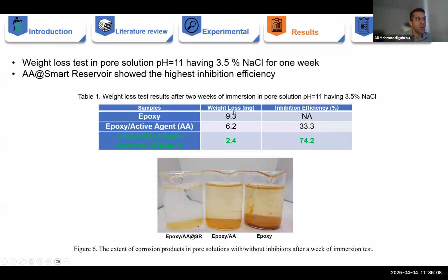And then we observed 9.3 milligram of weight loss for control sample with a lot of rust at the bottom of the beaker, and 6.2 milligram of weight loss for epoxy coating containing active agent, and only 2.4 milligram weight loss for epoxy coating containing a smart nano reservoir. And the extent of the rust, as you see, is substantially lower than two other samples.